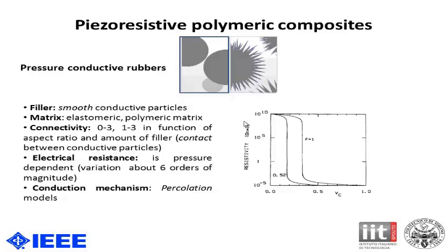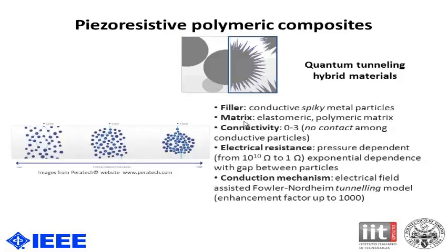Electrical resistance varies with the pressure by about 6 orders of magnitude, and the conduction mechanism between the particles is the percolation model. The other great type of piezoresistive rubbers is quantum tunneling hybrid-based materials. The fillers are conductive spiky particles, and the fundamental part is the spikes, because thanks to the spikes the electric field increases, and it is possible to apply the conduction mechanism of the Fowler-Nordheim tunneling model.